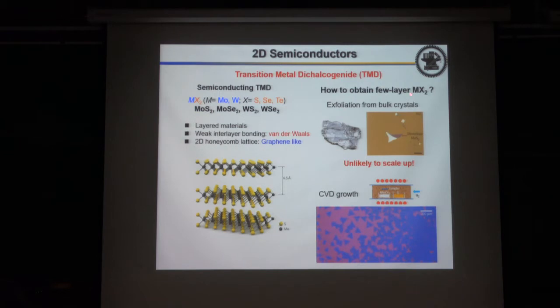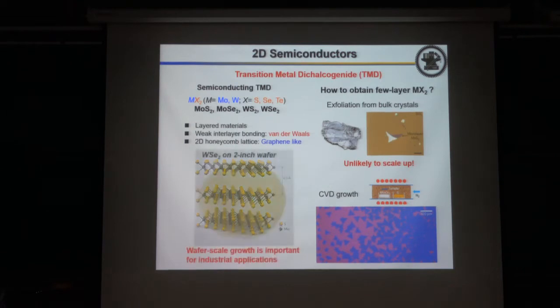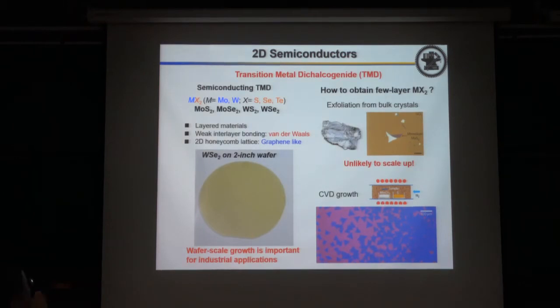In this way, it is, I would say unlikely, actually it is impossible to use exfoliation in TSMC. TSMC does not use exfoliation to produce large-scale electronics, right? Anyway, if you want industrial application, all the technology has to be scalable. So you can use this technology to fabricate wafer-scale and also larger-scale device fabrication. Now we can use CVD growth to grow the material on a 2-inch wafer, and actually this is limited by the size of our CVD system.